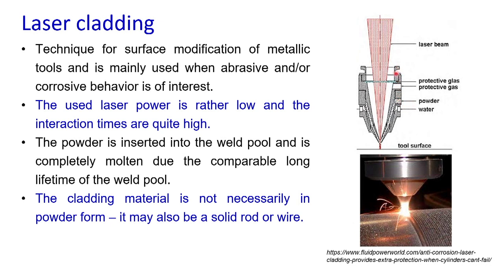So this is a typical nozzle of the laser cladding equipment. This nozzle has an opening through which the laser beam is applied over the surface. It has a protective glass and there is an opening in the nozzle through which we apply the protective inert gas as well. There is an opening for powder that is to be applied at the tool surface, and we also require water. Water here is being used to chill, to apply convective heat transfer to take away the extra heat generated during this operation. To safeguard the nozzle from excessive heat, chilled water is being used.